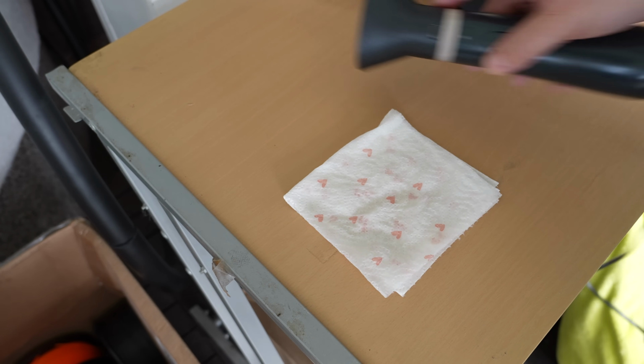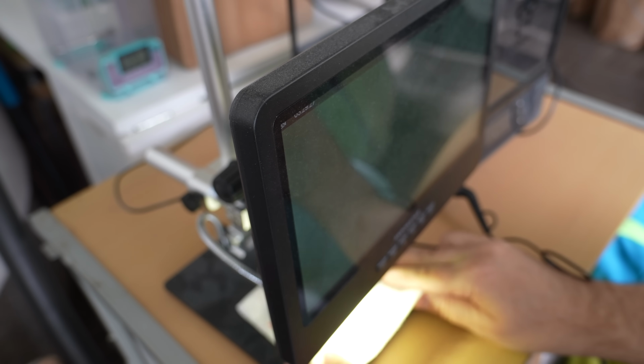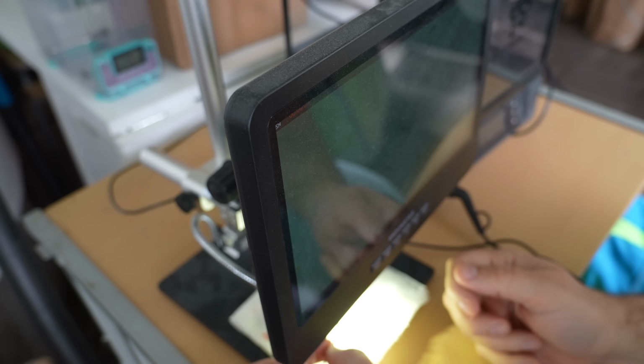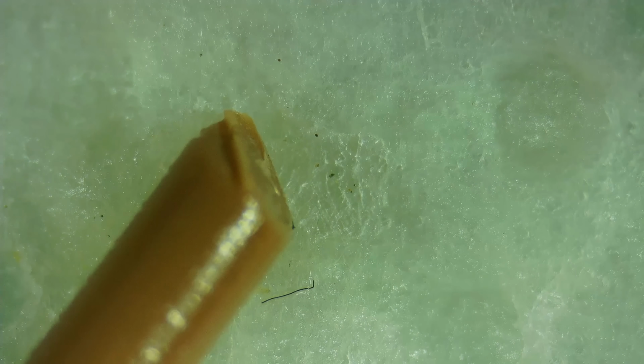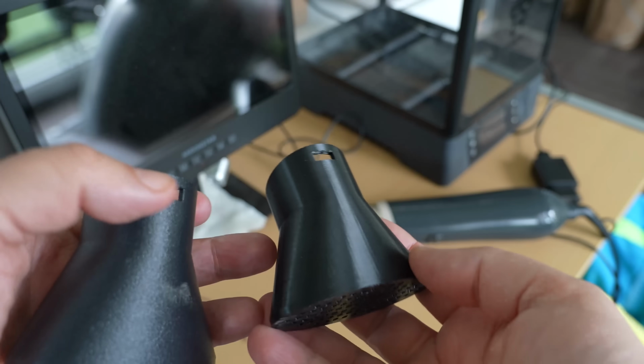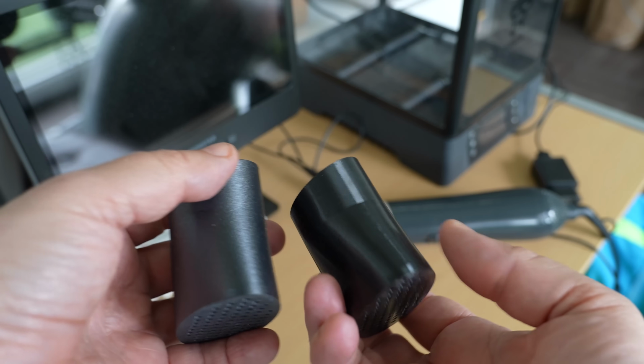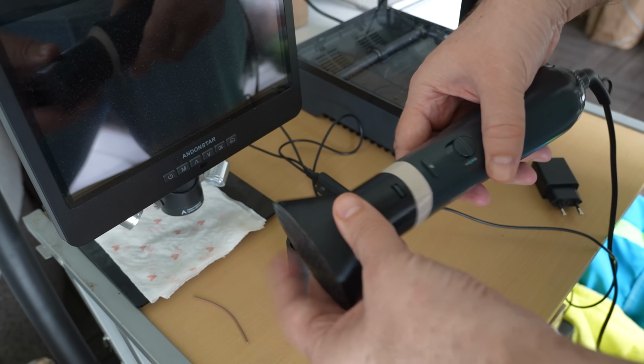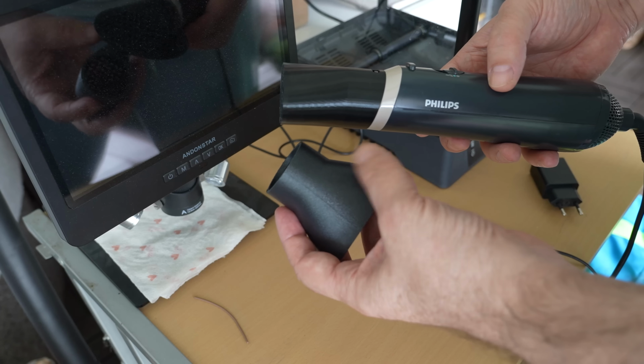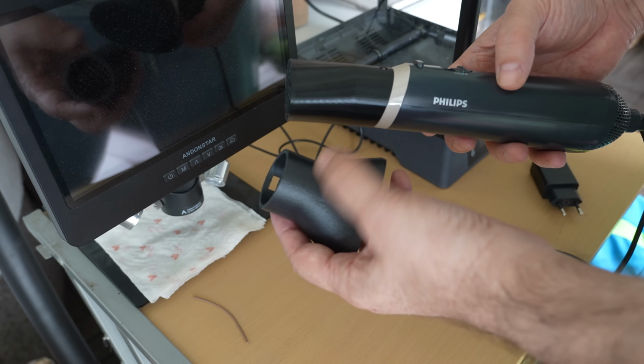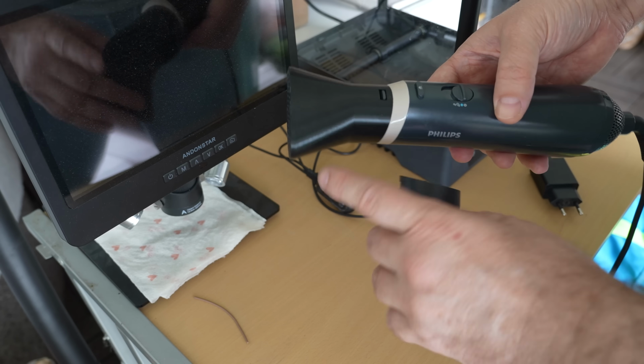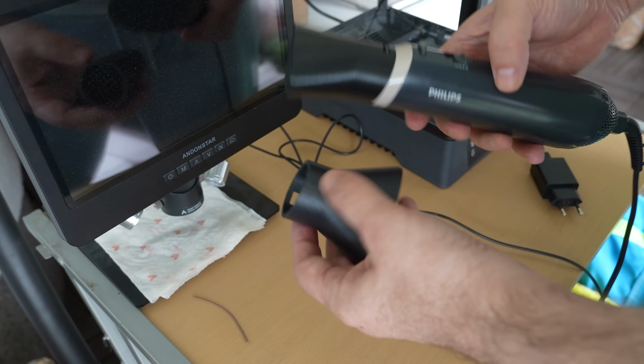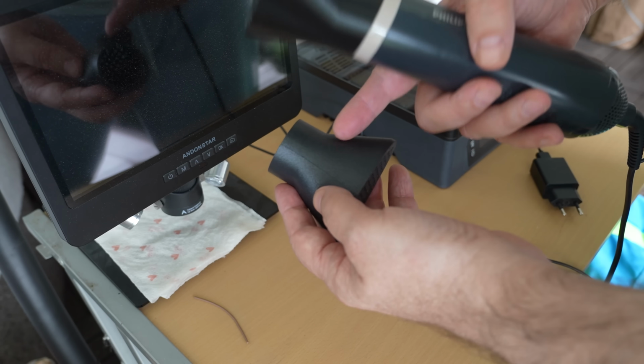Okay, it's still wet. Let's check it under the microscope. Actually, I find something, but I'm not really sure. This bigger one is probably not a fiber, because here you can see the filament, so it is too big. But there are those smaller black spots, and since I'm not 100% sure, just in case I reprinted this from the flame retardant polycarbonate. I still think that PPS may be better because of the higher temperature resistance, but in this case I feel more comfortable if you don't have those fibers, but there are many other applications where we can use this material.